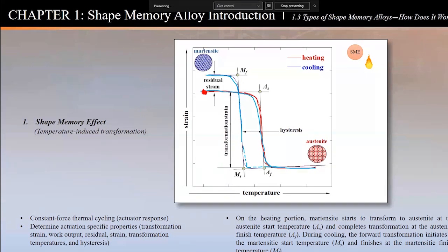So now I keep heating around here, nothing happens. No change in dimension. The strain could be displacement, could be twist, could be elongation, could be shrinking, whatever the component might do. Now when I'm cooling back, I'm going to cool my material. You start cooling until you reach a critical temperature, known as MS, which stands for martensite start. That's where you start the martensite transformation, and you go all the way up here until you finish the transformation, martensite finish, and then you go back to the starting temperature.